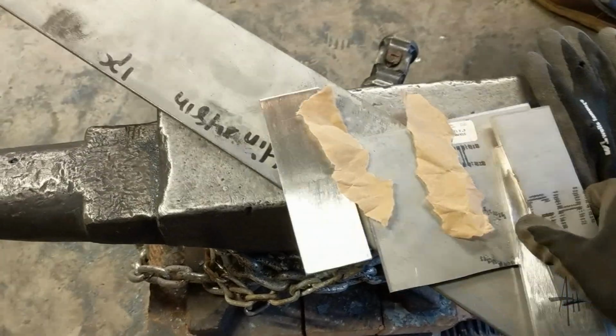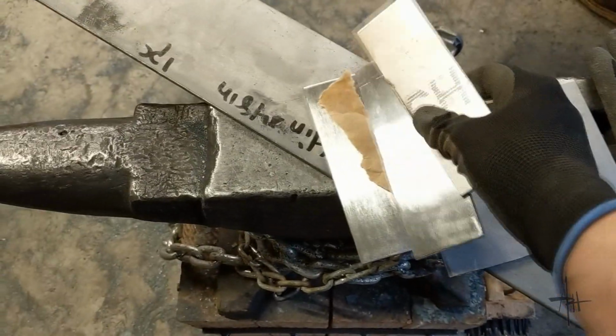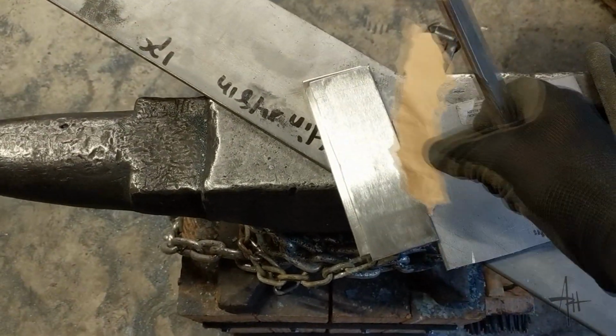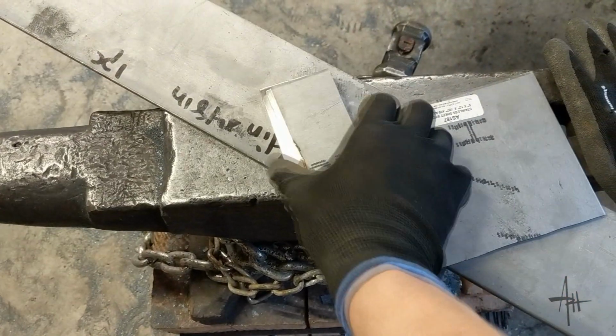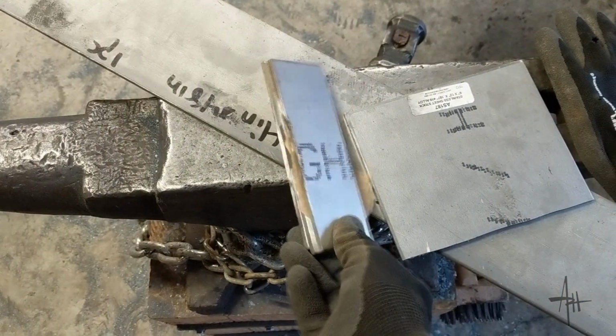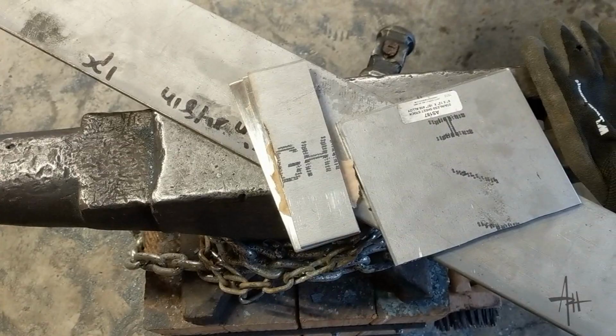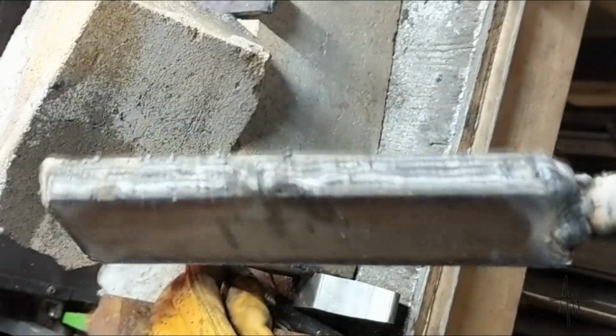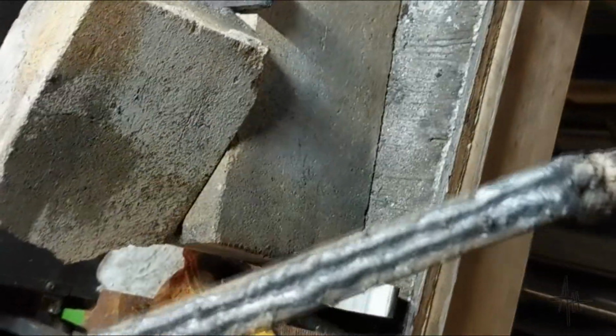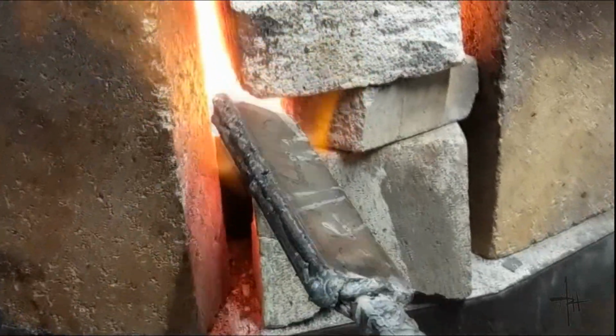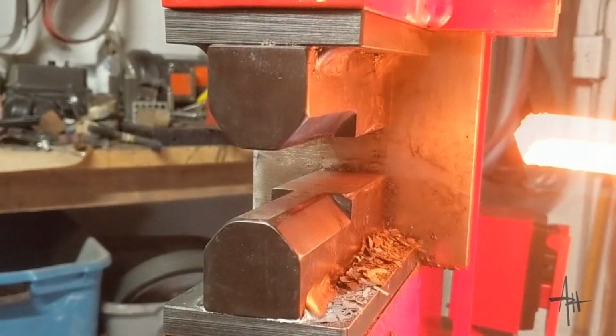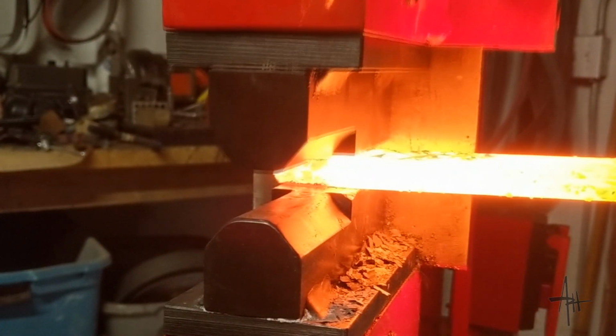The trick to making this fuse well the first time is to use a strip of paper in between each of the layers of the billet and getting a nice, tight, clean weld all the way around every exposed surface of the billet. Now, be sure and take your time when you do these welds because they are very important. It has to be totally airtight before you throw it in the forge to prevent any kind of decarb or oxidation. Once your billet's up to temp, it's time to forge weld it.